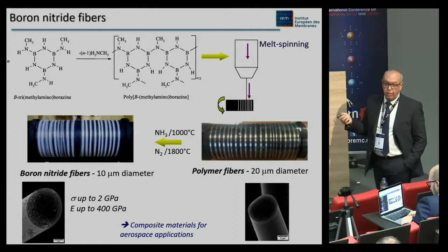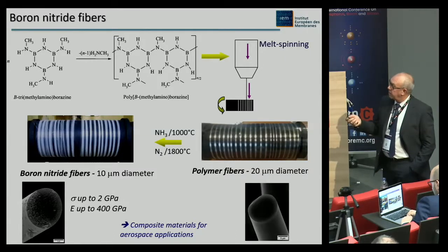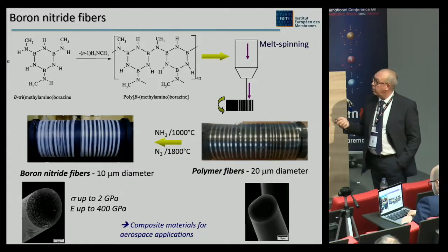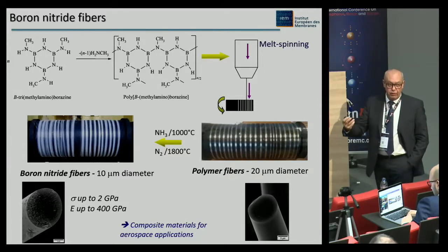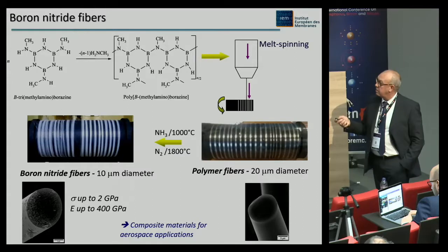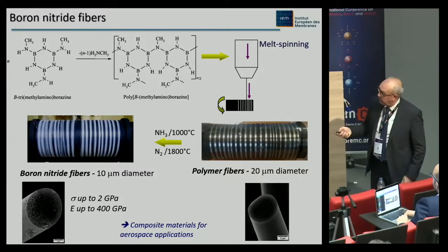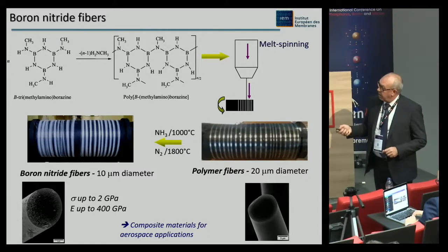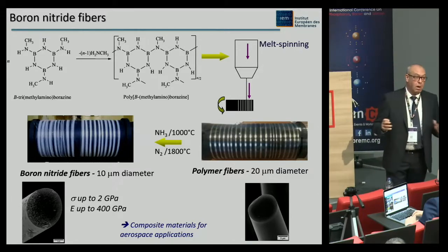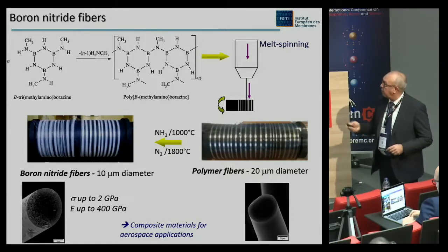After that, you have to convert your polymer into ceramic, so you have to remove the organic groups, and for that you have to treat the polymer fiber under ammonia up to 1,000 degrees, and at this stage, you obtain an amorphous ceramic. If you want a crystalline ceramic, you have to treat it in a second step under nitrogen up to 1800 degrees to obtain these very nice BN fibers of 10 microns in diameter. They are polycrystalline, and they display tensile strength up to 2 GPa with a very good Young's modulus also. And just for details, these materials have been developed for composite materials for aerospace applications.